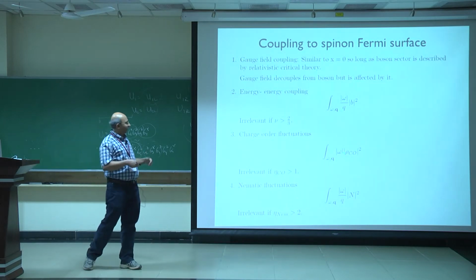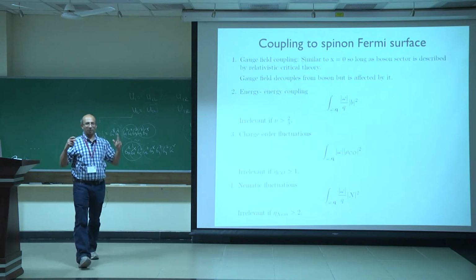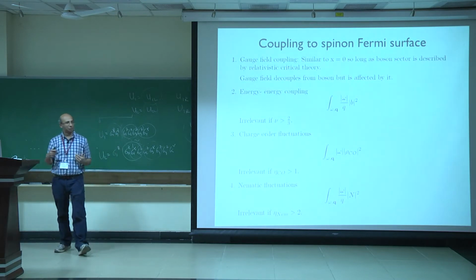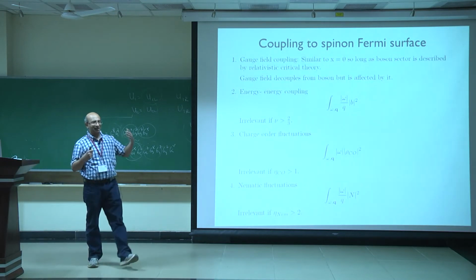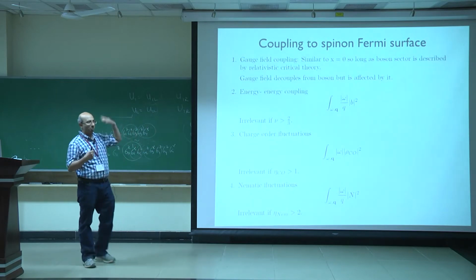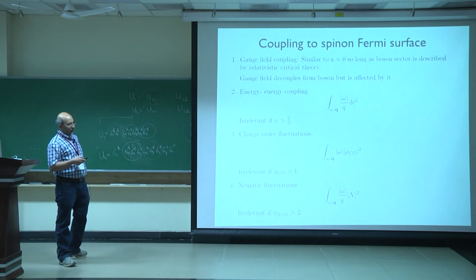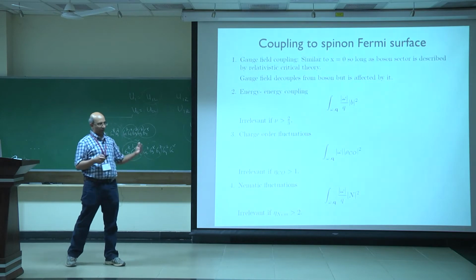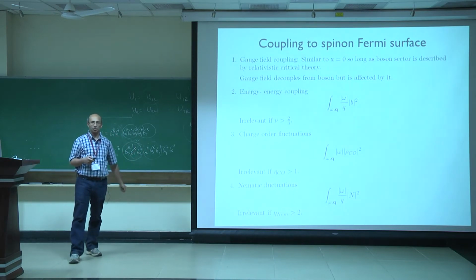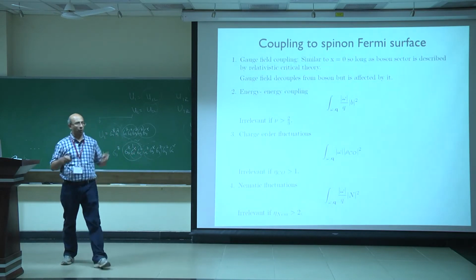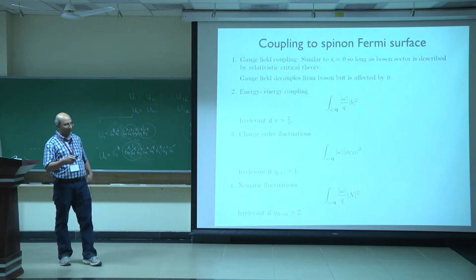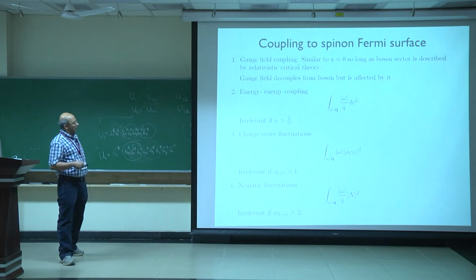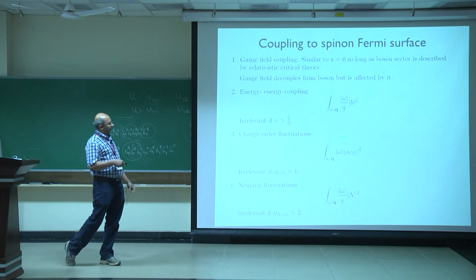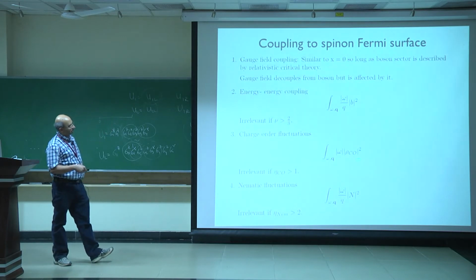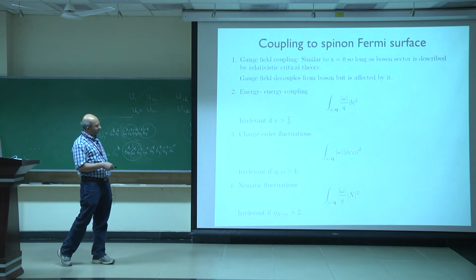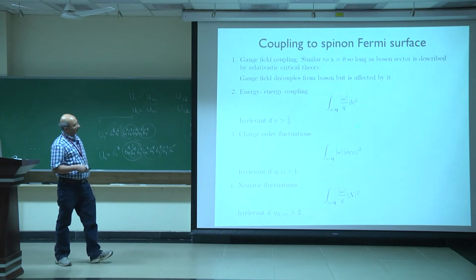Now the charge order fluctuations, in the language of this putative deconfined criticality associated with the boson sector, the charge ordering is what we call a monopole operator. It's of the kind that Ribhu was calculating in great detail. It's an instanton for the appropriate gauge field. So usually at the deconfined critical point, those sort of single monopole operators are not allowed. Ribhu mentioned that only quadruple monopoles are allowed at half filling at q equals 2. But here, there's a term that's linear in this charge CDW order parameter that's allowed.